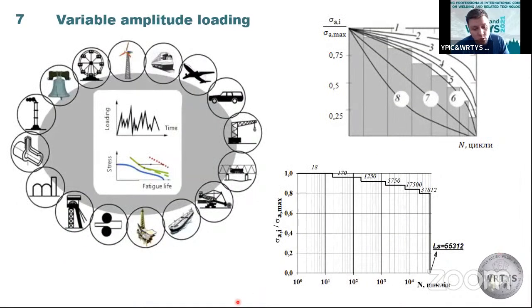But the main issue of parts welded with this alloy is the fatigue behavior of this alloy. As we know, many structures work not only under constant amplitude loading, but mainly under variable amplitude loading.